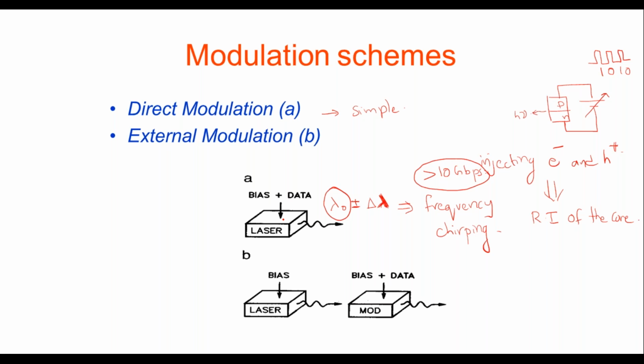Nowadays we always want to send information at very high speeds. You always want your internet speed to be very high, right? So you always want to send signals at speeds exceeding 10 gigabits per second. And when you are sending signals at speeds exceeding 10 gigabits per second, this frequency chirping happens, which means that unfortunately direct modulation is not a feasible modulation technique, and therefore we go for what is called the external modulation scheme. This external modulation scheme is what is being shown here.